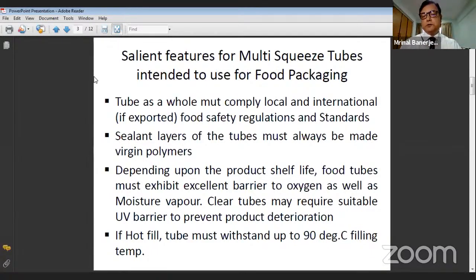So generally for food tube, even for oral care, if it is aluminum, it automatically comes, depending on the thickness of the foil and pinhole counts, to 0.2, 0.3. If it is oxygen, it's like 0.2, 0.3 cc per square meter. And if it is moisture, that is also around 0.2, 0.3 grams per square meter in 24 hours. So these are very important.